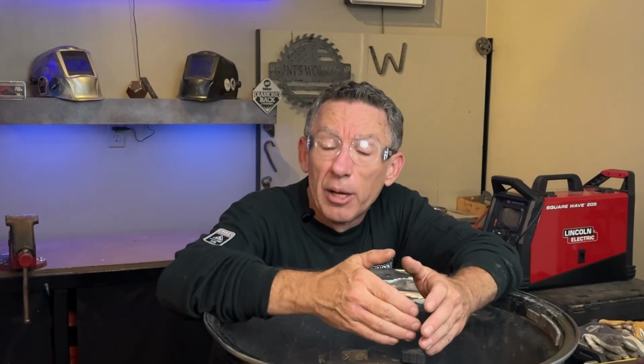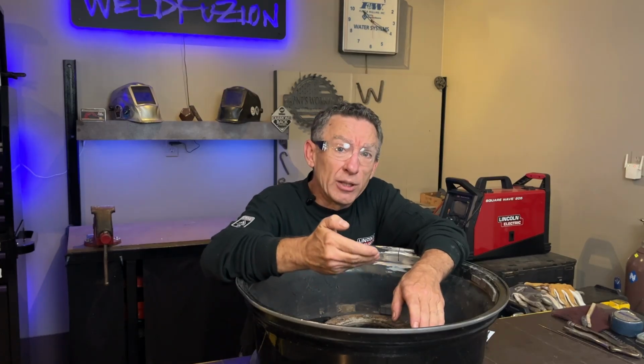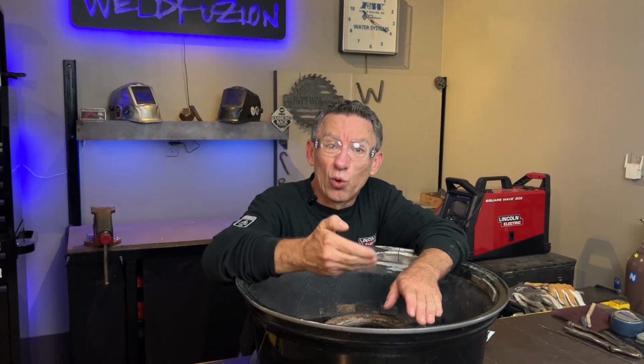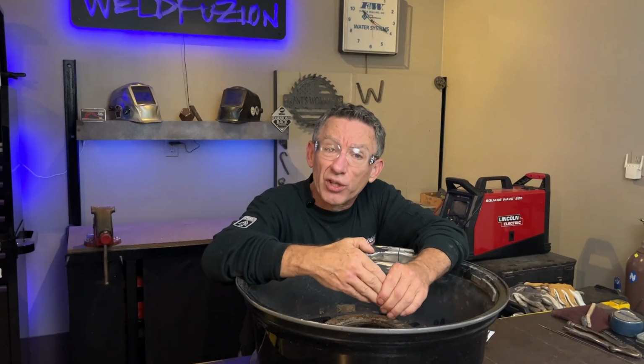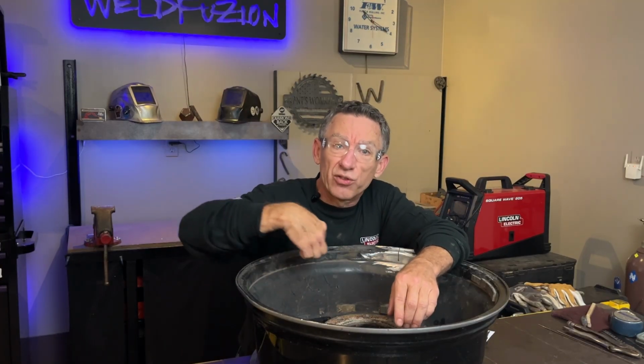At the same time, hardenable alloys go through a process called aging or artificial aging, where they're heated to about 400 degrees and held there for a period of time. And to a certain point, that increases strength. But after a period of time, it actually causes it to get weaker. It's called overaging. So we don't want to heat the aluminum up anywhere near that potential. At the same time, it's going to be cold worked. And sometimes those materials undergo strain hardening. So the higher we heat the base metal, the more chance we're going to anneal any of that cold working. And I'm not so sure we want to do that in this case, right? Because we're deriving strength from the way this thing is shaped and formed. That's my take on preheating aluminum and the dangers of it.